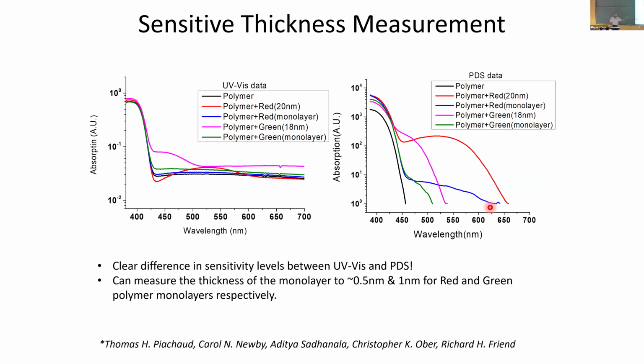This sample actually goes into LEDs. We want a very precise recombination layer, a precise monolayer where all the electrons and holes recombine to give you light. We wanted to know whether it's a monolayer or not, because this is all solution processed, and it can result in several layers, or no layer at all because it gets washed off.